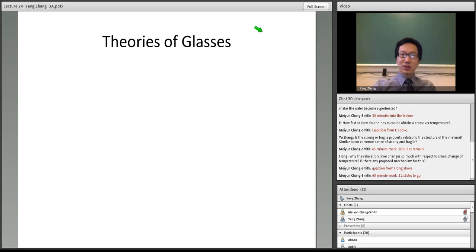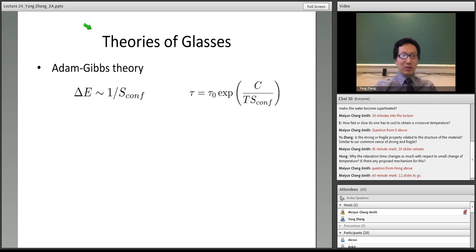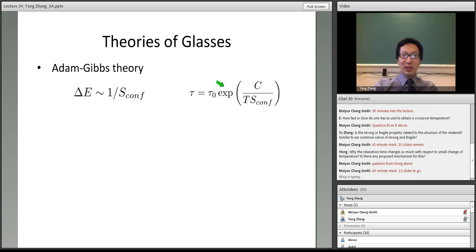Now let me spend a few minutes to review some basic theories of glasses. Again, the number of theories of glasses is so many that we cannot cover all of them, but a few important ones are listed here. The first one I want to mention is the so-called Adam-Gibbs theory. The concept is very similar to the dynamic heterogeneity. Consider these regions where several particles need to rearrange themselves. According to the theory, the activation energy should be inversely proportional to the configurational entropy of the system. And then the relaxation time goes like an Arrhenius behavior.